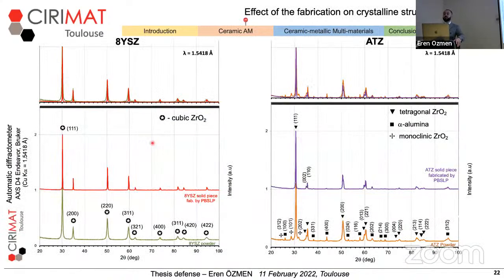So the next question was, what was the effect of fabrication on the crystalline structure of pieces? Here we see first the powder of 8YSZ and ATZ before the lasing process, and then we compare them with the solid pieces after fabrication. For 8YSZ, the first thing that takes attention is the remaining cubic phase. As no new peaks appear or any peaks disappear, and by comparing with the XRD database, we say that the cubic phase is retained.